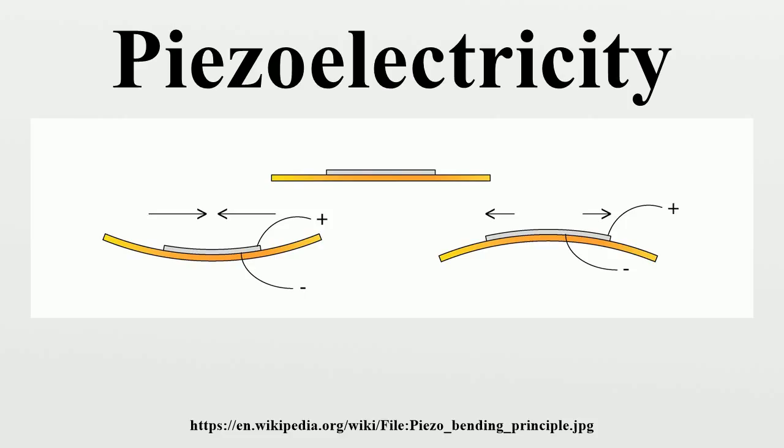For example, lead zirconate titanate crystals will generate measurable piezoelectricity when their static structure is deformed by about 0.1% of the original dimension. Conversely, those same crystals will change about 0.1% of their static dimension when an external electric field is applied to the material.